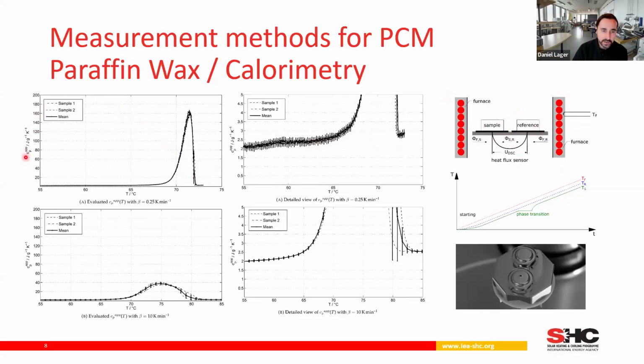For example, here you see the apparent specific heat capacity of a paraffin wax with a melting temperature at around 70 degrees C. So you have here the sensible part where you heat up the solid, then you get into the melting, and then after the melting, you're in the liquid phase. When you now look into the detail of this curve, so this is a focus of this temperature range, you see here high uncertainties because of the heating rate you use in the system. When you use faster heating rates, which is shown here in the pictures below, you see that this peak is broadened and the peak height is lower, but the uncertainty here is much lower.